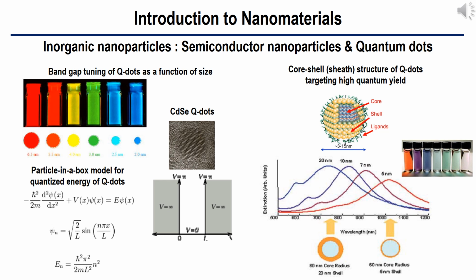The quantum efficiency or quantum yield is the ratio between the absorbed energy and the energy of the luminescent photons. For example, cadmium selenide quantum dots have 5% quantum yield. This is due mainly to the high concentration of defects such as trap states. To overcome the low quantum efficiency, researchers have developed core shell structures in which core and shell have different electronic structures. For the higher quantum efficiency, the two electronic states can be matched to minimize diffusion barrier, defects concentration, and scattering of electrons at the core shell interface. This makes the quantum efficiency notably high. For example, cadmium selenide core and zinc sulfide shell quantum dots show quantum efficiency higher than 50%.